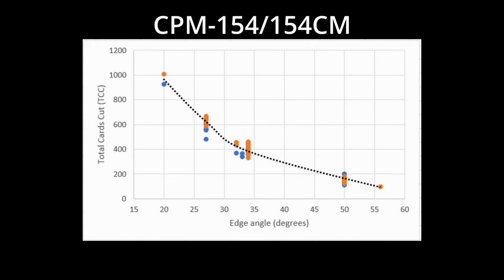In a CATRA study on 154CM and CPM 154, they varied the angle from 10 degrees per side all the way up to 28 degrees per side, or 20 to 56 degrees inclusive angle.